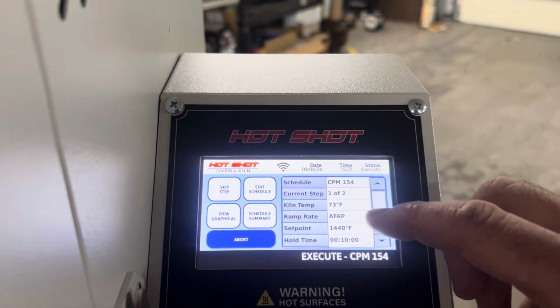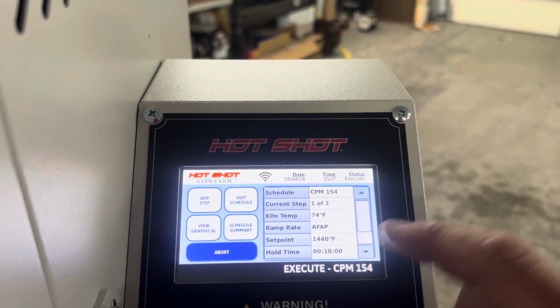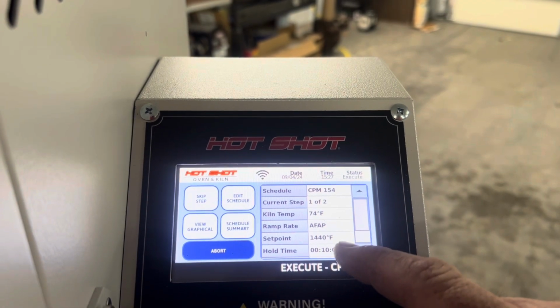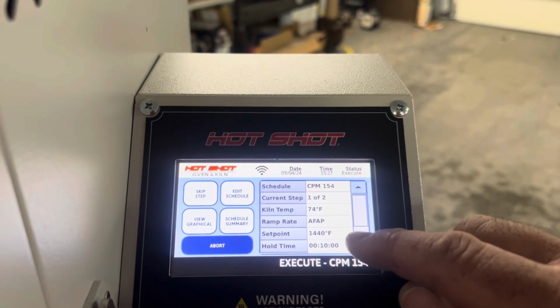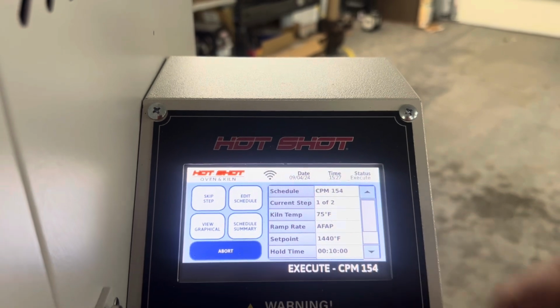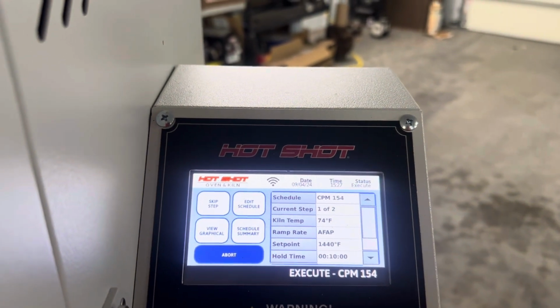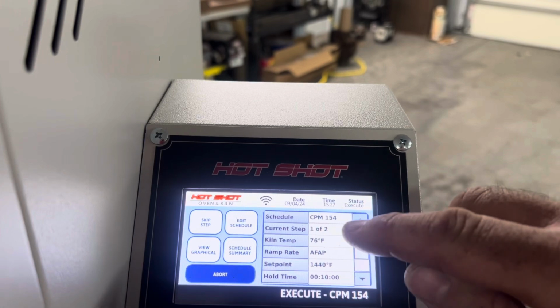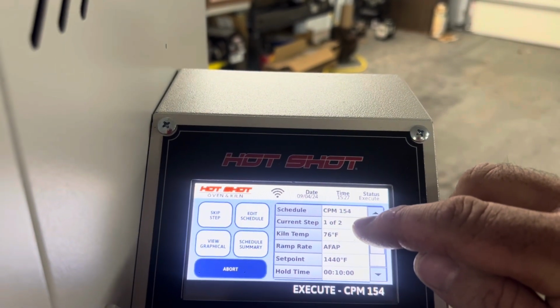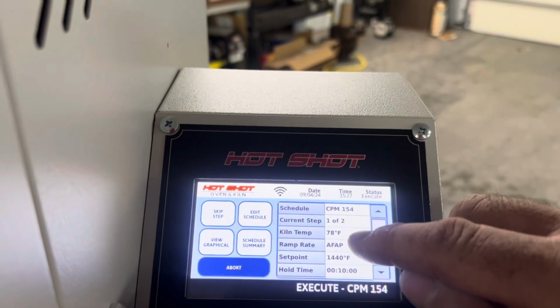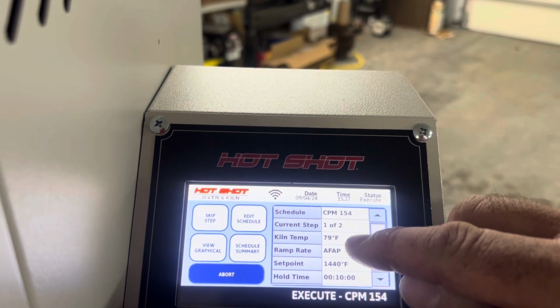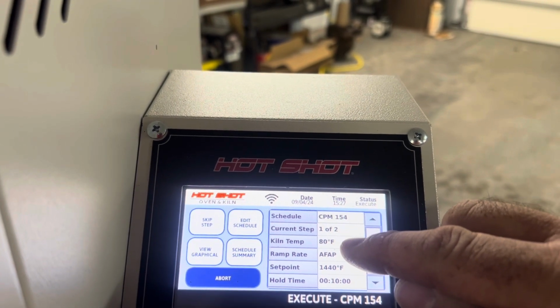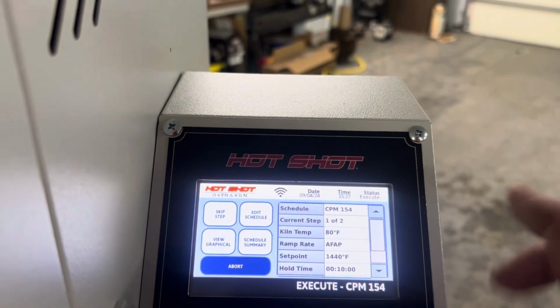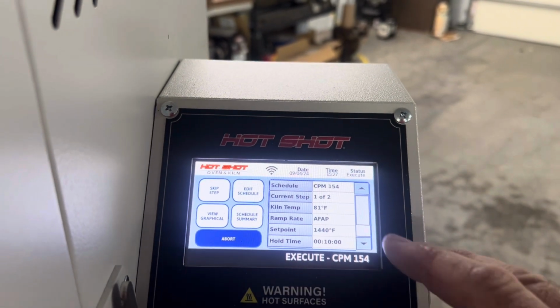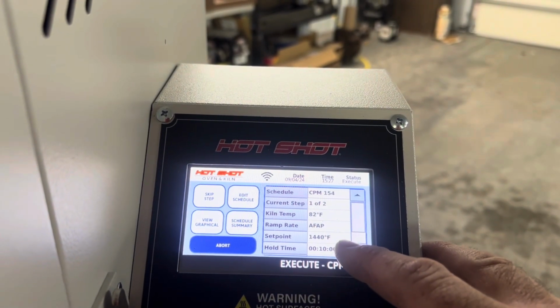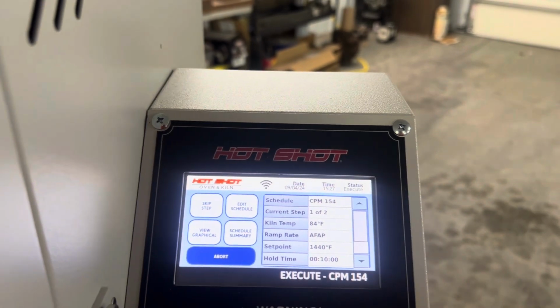The ramp rate is as fast as possible. The set point is going to ramp up to 1440 degrees. It's going to hold it for 10 minutes. The program is initiating right now, and this is currently step one of two steps. Again, we'll ramp up. As you can see, the numbers are climbing now, 78, 79, 80, and we will ramp up the oven. We'll ramp it up to 1440 and hold it for 10 minutes, and then it'll automatically